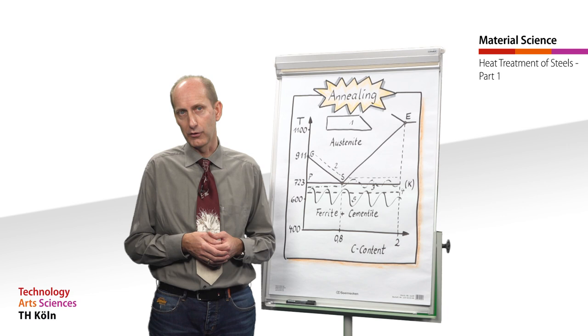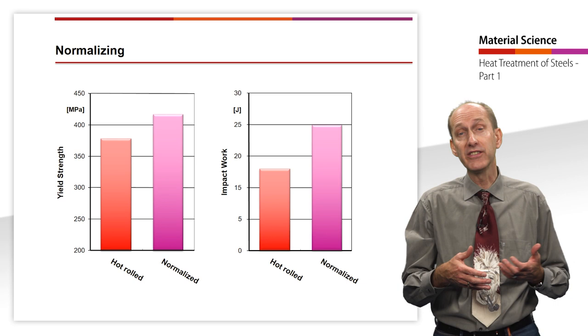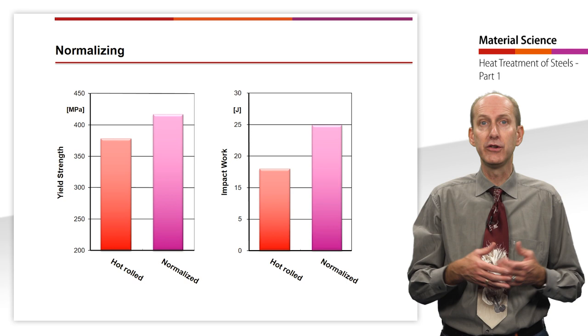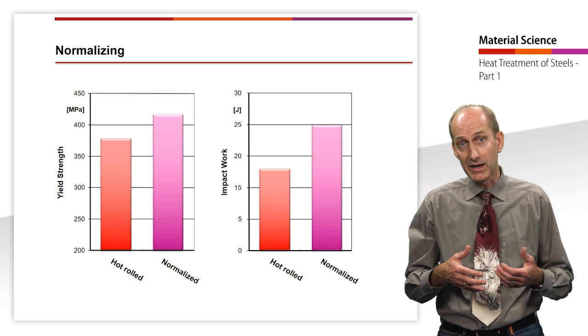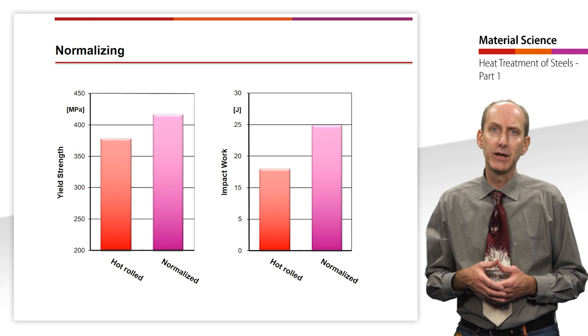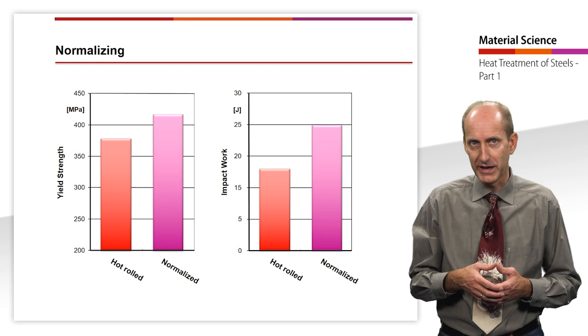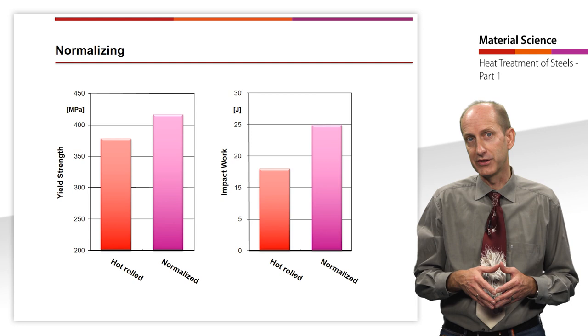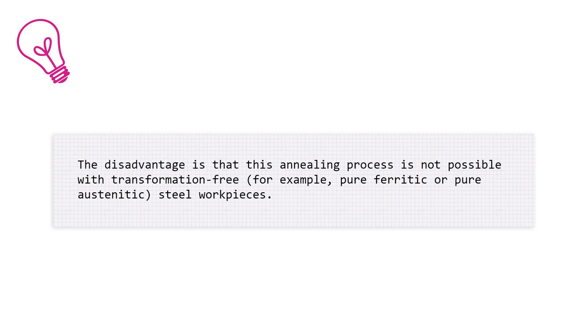Modern rolling mills offer the possibility of adjusting the roll temperatures and cooling so that normal annealing can be replaced by this rolling with controlled temperature control. These are then referred to as normalizing rolled steel samples. Normalizing improves all the impact energy responsible for brittle fracture behavior. The transition temperature is also shifted toward lower temperatures. The disadvantage is that this annealing process is not possible with transformation-free, for example, pure ferritic or pure austenitic steel